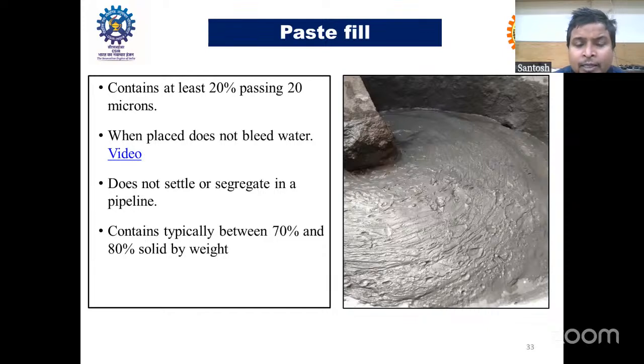And also in terms of particle size, in hydrofill it is better to use a backfill material which has a lesser amount of fines, whereas in paste fill the material should have sufficient fines. Sufficient fines means particles less than 20 micron have to be 20%. And bleeding, meaning separation of water from the solid material, should be minimum. And during the transportation of paste from the surface paste plant to underground, it should not settle or segregate within the pipeline, and normally it contains high solid. In the right figure you can see the paste fill, something like toothpaste.